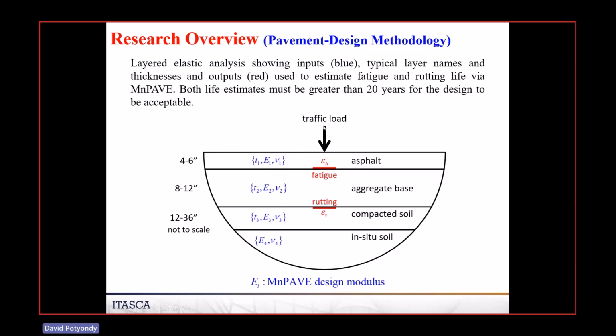This is the typical traffic load. It pushes down, and what it does is deflects this. And there's 2 types of failure that occurs. You get horizontal strain here. This thing is pulling. This is a beam. It goes into tension, and every time you load it, there's little cracks that grow more and more as a fatigue loading. You might have 3 million cycles of load on a typical roadway until you reach 20-year design life. The other thing that happens is this soil starts to fail locally. And therefore, when this soil fails, this whole thing goes down, and you get what are called ruts.